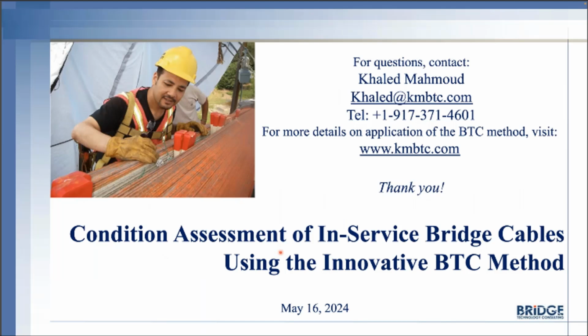One more question here, and I'm going to turn it over to Jamal. Some people have used ambient vibration to measure existing forces in tendons. What do you think about this method of inspection? Well, it has some merit when you have a single strand or a single wire, and you can get some good feedback. But on a suspension cable, where you have the wire surrounded by other wires, the interaction and friction between the wires would change the boundary conditions, so it might not be spot on. It's a good guesstimate of the tensile stress in the cable. But remember, damage is a local phenomenon. And when you have these particular cracks and the crack growth, I doubt that the ambient vibration method would capture that, because there is a redistribution of the stress in the remaining wires. So it has to be taken with a grain of salt.